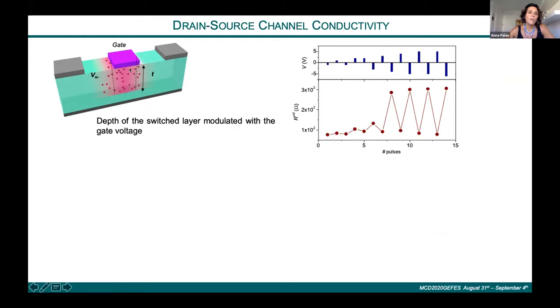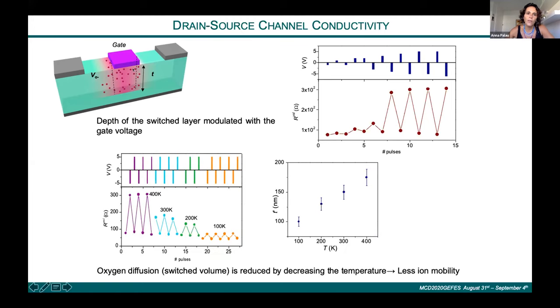For example, here we have evaluated the diffusion of the oxygen below the gate, considering different applied voltage pulses. We observe that this thickness is increased by increasing the voltage pulse. And also, we have observed that this distance of the oxygen diffusion depends on the temperature.